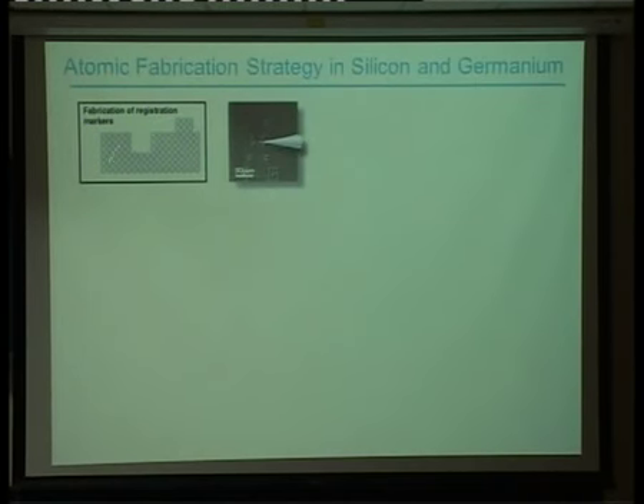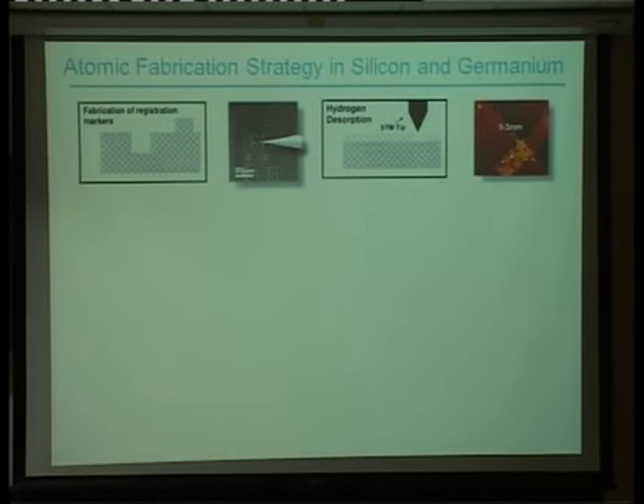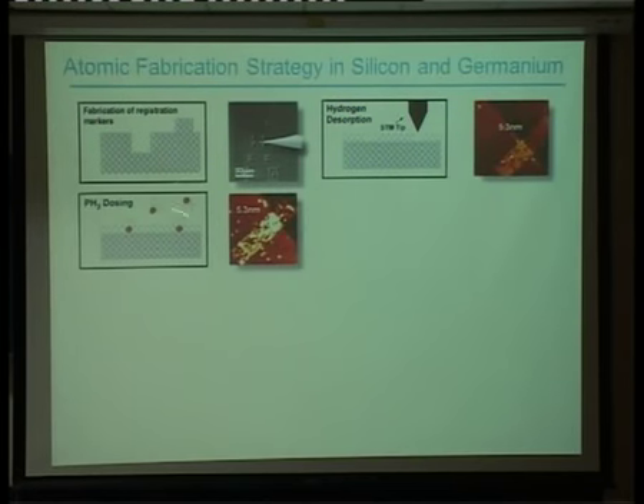So the key step is the registration markers. These are things you need to make outside of the STM, so you make them in a clean room before you put the sample into the system. You then come down with your STM tip with respect to these markers. You hydrogen terminate the surface, and then you dissolve the hydrogen with the STM tip to expose the silicon underneath. That's how you create the atomic scale mask. And these bright regions are where the hydrogen's been removed. You then bring in your phosphine gas, which only absorbs to the exposed regions on the silicon surface and doesn't attach to the resist layer around it.